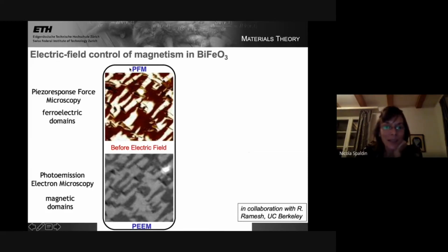This is a measurement of the top surface of a thin film of bismuth ferrite, the first of the two multiferroics that we looked at the start. The picture is taken with a technique called piezo force microscopy, which measures the opposite orientations of the ferroelectric dipole, the so-called domains of ferroelectricity. The white regions correspond to the electric dipole pointing, say, out of the page, and the brown regions to the electric dipole pointing into the page, or the other way around. It doesn't matter which, but they're opposite. And this is a picture of just the as-grown sample. So nothing's been done to it. There's been no electric field applied. It's just how it came out of the growth chamber.